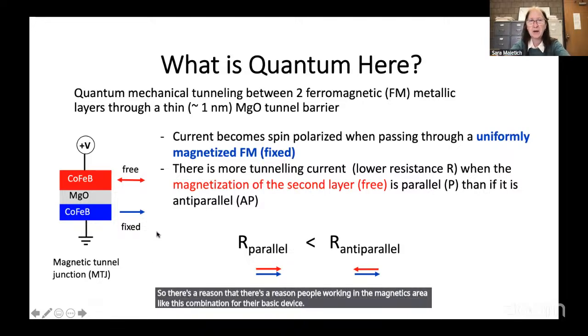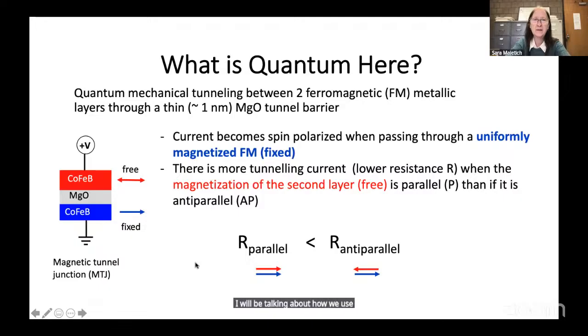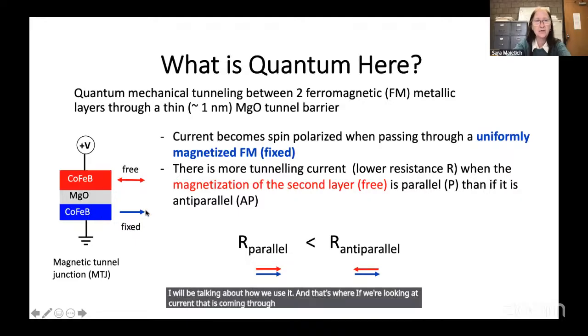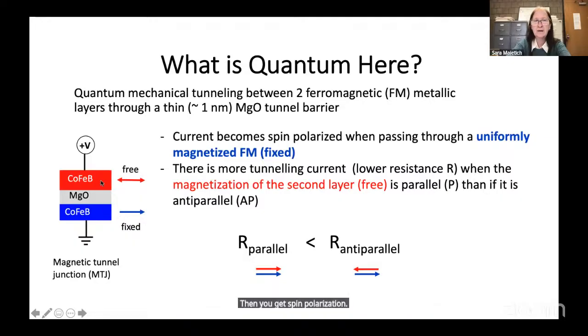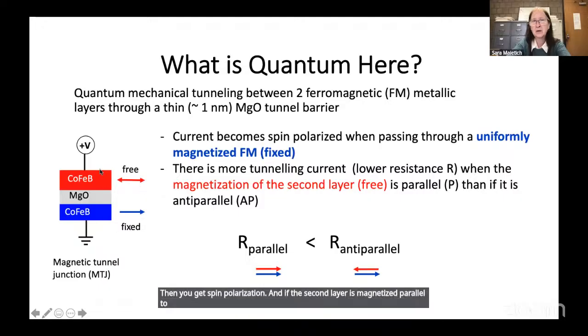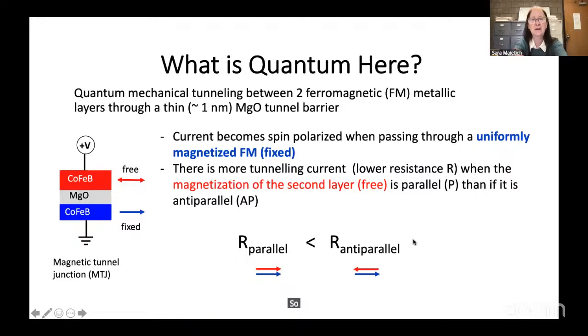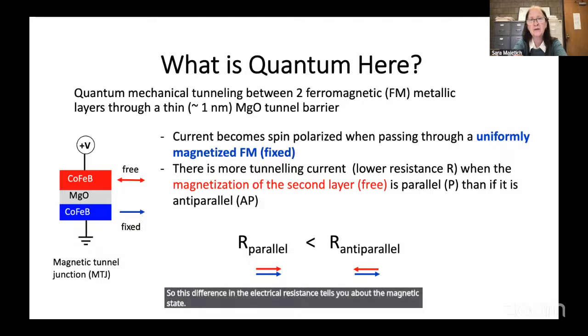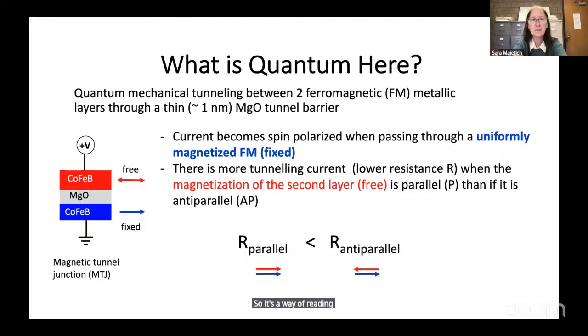I'll be talking about how we use it, and that's where if we're looking at current that is coming through one of these layers that's uniformly magnetized, then you get spin polarization. And if the second layer is magnetized parallel to it, there's more tunnel current than if it's anti-parallel. So this difference in the electrical resistance tells you about the magnetic state. So it's a way of reading the magnetic state of your tunnel junction.